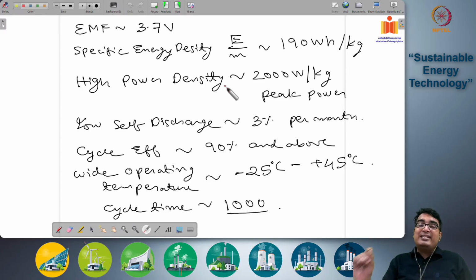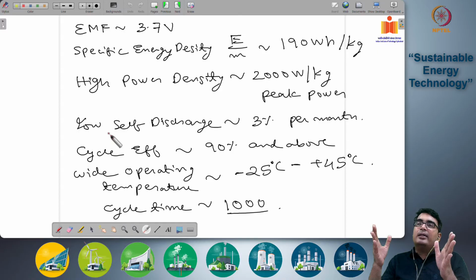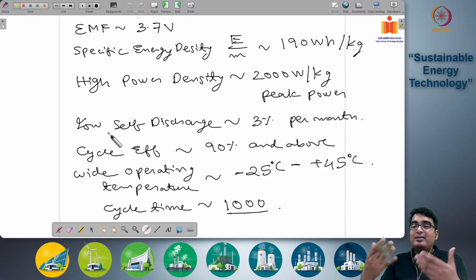Further, it is extremely stable. It has a low self-discharge rate, only 3% per month. So a new, well-designed lithium-ion battery can be switched off for over 1 or 2 months, and when it is turned back on, it will still have charge. So it has a very low self-discharge rate and hence is long-lasting. Even slow cycles it can handle. And it has a very good cycle efficiency of 90% and above. So you are getting more than 90% of the energy back that you originally put in.